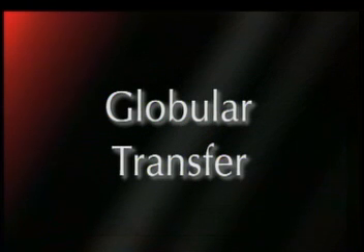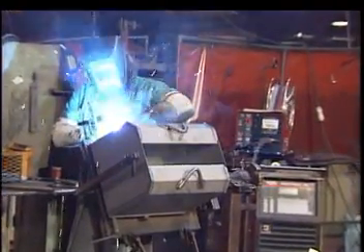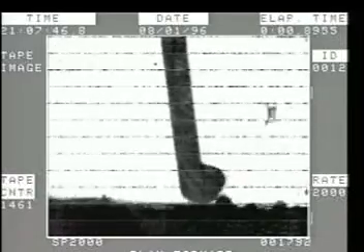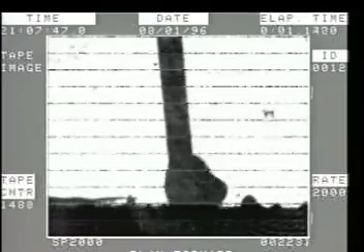Globular transfer uses higher energy levels than short arc and higher wire feed speeds. This process offers very fast fill or high-speed characteristics, high deposition rates, and very good penetration. However, when viewed up close, globular transfer exhibits extreme violence in the arc. The violence of the process is shown by the large droplet size. The arc is not forming anywhere on the droplet, and a current density high enough to pinch off the droplet cannot be reached.